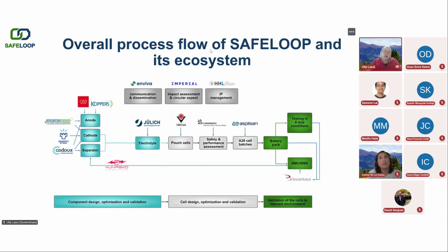And once again, to fulfill the criteria of the recycled content, we use recycled elements from batteries, spent batteries, and also a thin alumina coating layer, and this alumina is also a recycled element.